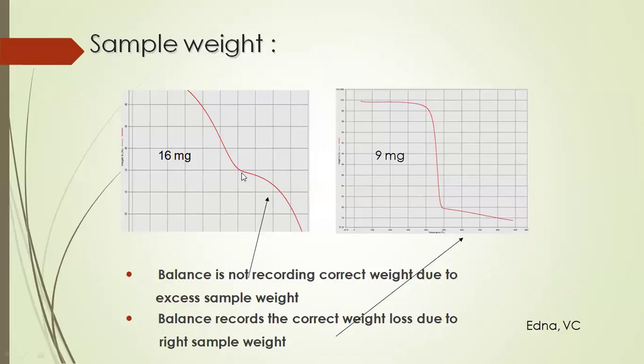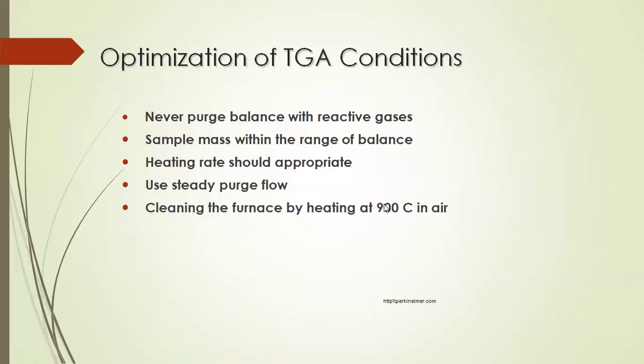You will end up with a curve from which you cannot extract any information. But if you reduce the same sample weight to below the capacity of your balance, you end up with a nice TGA curve where you can extract whatever information you want, like onset, degradation, residue. So the balance records the correct weight loss due to the right sample weight. So the choice of the right sample weight is also very important when you do a TGA. These are the small tips to get a good TGA curve.